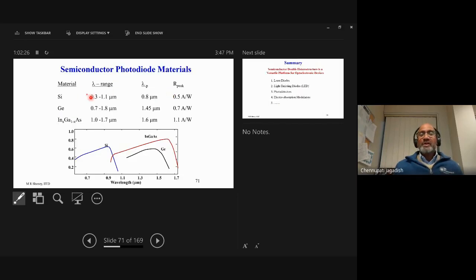Silicon covers 300 nanometers to 1.1 microns, the peak detection wavelength is about 800 nanometers, and the typical responsivity is about 0.5 amps per watt. Germanium is for 0.7 to 1.8 microns, the peak is about 1.45, and the responsivity is better. Indium gallium arsenide is even better. It covers the spectrum of 1 to 1.7 microns or so, and now extended InGaAs detectors can go to 2 microns or so as well. You can see the responsivity plot as a function of wavelength here.